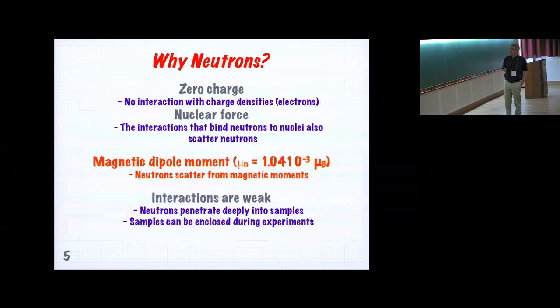And because of some of its other properties, we can actually have very complex sample environments. Until more recently, X-rays and other facilities couldn't do things at dilution temperatures, and we're kind of stuck at maybe 20 Kelvin. If you had a fantastic machine 20 years ago at a synchrotron, you got to maybe 4 Kelvin. As we know from what we're studying today, that would be a disaster for quantum spin liquids. That has changed. They put everything in a great big vacuum tank, so you can imagine this huge spectrometer with the dilution and everything inside a vacuum. It gets very complicated, and more often than not, things don't work.